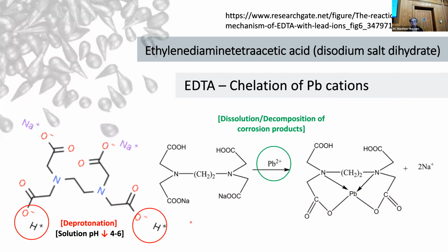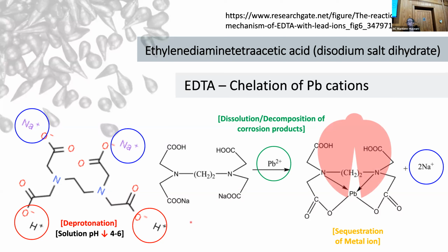So you have your deprotonation that happens, which creates your decomposition products, or your dissolution of your various types of lead corrosion products into more digestible ions, which then end up being sequestered by your chelating agent and then able to be removed essentially from play by being dissolved into the water as a result. And as you can see, the sodium still is hanging around here, and the sodium plays a pretty important function as well. In order to get that chelator operational, these sodium ions have to essentially leave the structure. They have to dissociate. They themselves have to go into solution and do other work. So then you leave these kind of activated oxygen molecules at the end of this functional group that can do work and bind to these metal cations.